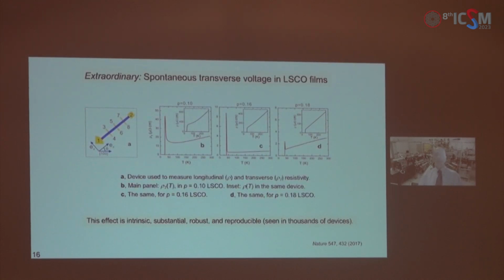There is more in the normal state that is quite extraordinary. One of these was the observation of spontaneous transfer of voltage, something like a Hall effect, except that we see it in zero field. This is not an experimental artifact. We have ruled it out by extensive experimentation for well over a decade on a couple thousand devices. We observed it for the first time in 2006, but we published it only in 2017, after we had seen it in thousands of strontium cuprate devices, without a single exception.